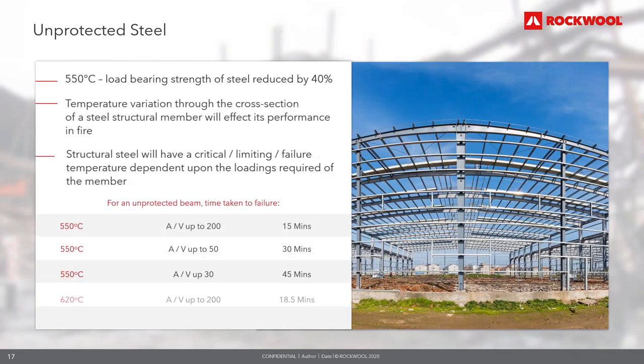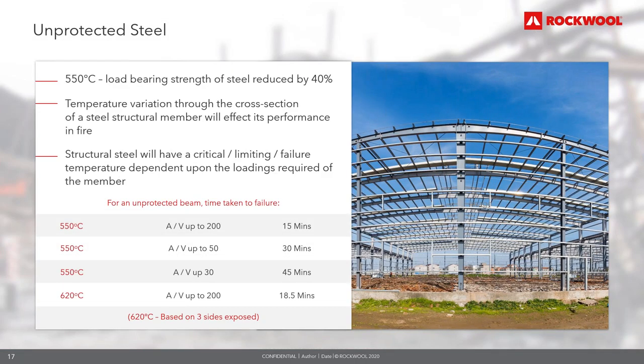So what happens if we leave steel unprotected? Steel generally begins to lose its strength at temperatures above 300 degrees C and eventually melts at around 1500 degrees C. Importantly for design, the greatest rate of strength loss is in the range of 400 to 600 degrees. It is necessary to limit the temperature rise of the steel, with 550 degrees C being a conservative temperature, mainly due to the fact that concrete, which it supports, acts as a heat sink.